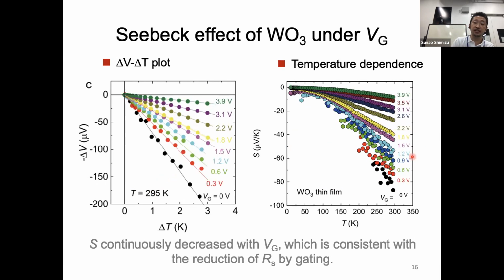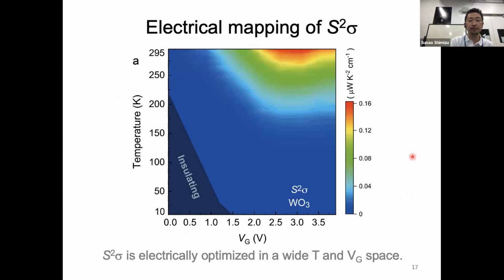We also measured the Seebeck coefficient and the resistivity of this material, so we can estimate the power factor. The result is here. This shows the power factor S squared sigma as a function of temperature and also gate voltage. Please look at the data around room temperature.